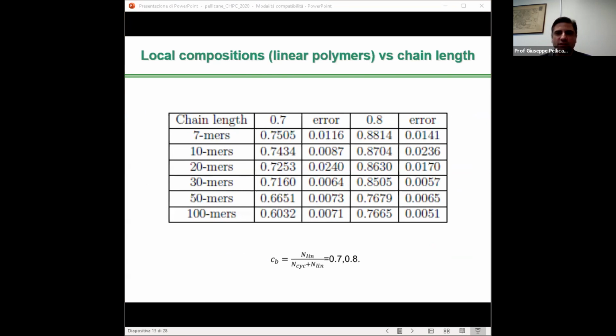Linear polymers enrich the surface in the case of short chains, while the opposite happens in the limit of long chains. This evidence of enhancement of linear polymers in the short chain regime agrees with what was recently reported in experiments conducted on linear-cyclic polystyrene blends. The molecular mass of the two polymers used in those experiments corresponds to roughly 10 to 13 beads per polymer by using the bead-spring model, with some assumption on the value of the entanglement length.